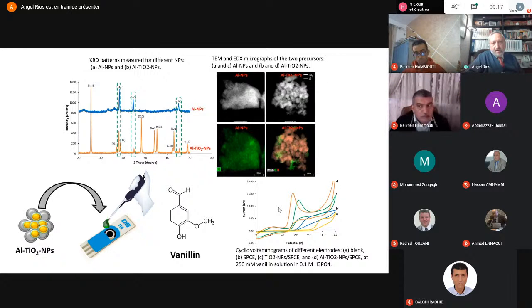And you can see here in this slide the information provided by a microscopic technique in order to check the introduction of titanium dioxide nanoparticles in the aluminum nanoparticles, and also X-ray diffraction in order to check, in the recording, the characteristic peaks of this nanomaterial incorporated in the aluminum nanoparticle. The modification of the screen printed electrode is very easy, as you can see in the illustration in the slides, for the determination in this case of vanillin in different types of food sample, and the corresponding electrochemical recording in order to perform the determination.